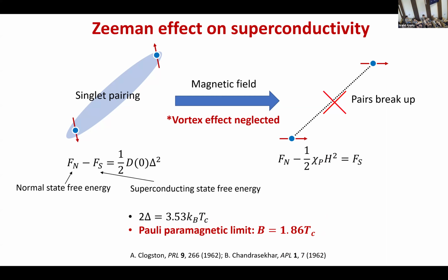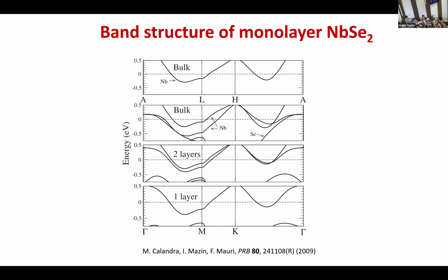And that means that if we have a 2D superconductor with a Tc of, say, 3 Kelvin, then when you apply an in-plane field of 6 Tesla, you should be able to suppress superconductivity, which is not the case in the niobium diselenide monolayer. So the magic happens for the niobium diselenide monolayer.